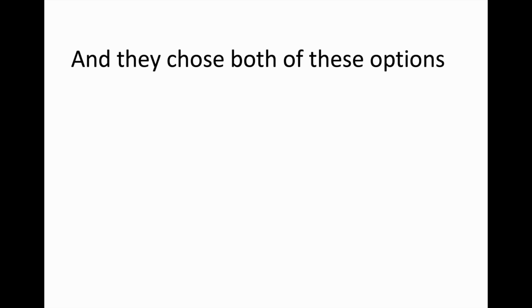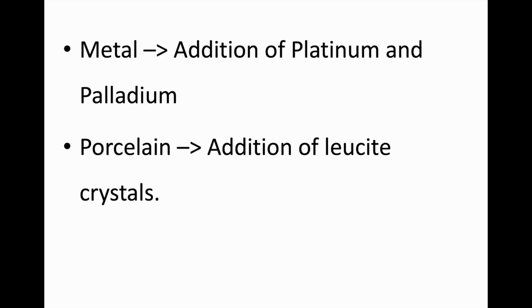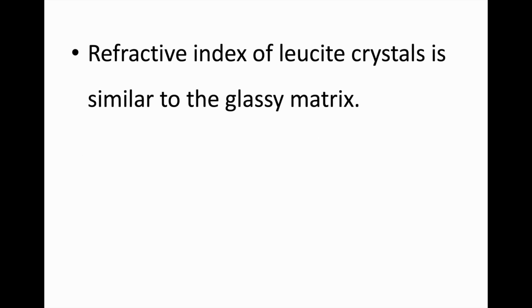And they chose both of these options. The coefficient of thermal expansion of metal was reduced by the addition of platinum and palladium, whereas the coefficient of thermal expansion of porcelain was increased with the addition of leucite crystals. One more reason for choosing leucite crystals was that its refractive index is similar to the glassy matrix, and when light falls on it, it will not be scattered. Hence the aesthetics will not be hampered.